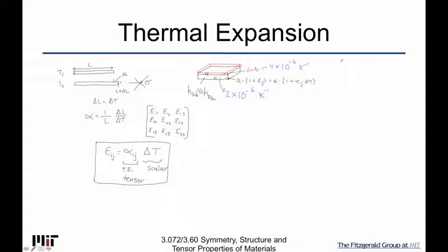So you actually induce a stress from this as you cool down. And because it's under tension, it's the worst case because we all know that a failure mode for tension is cracking. And so you can develop cracks in this film as it's cooled down.